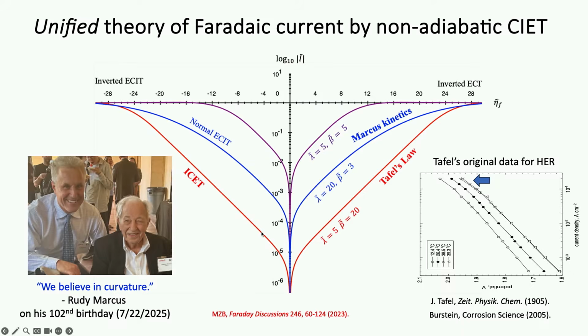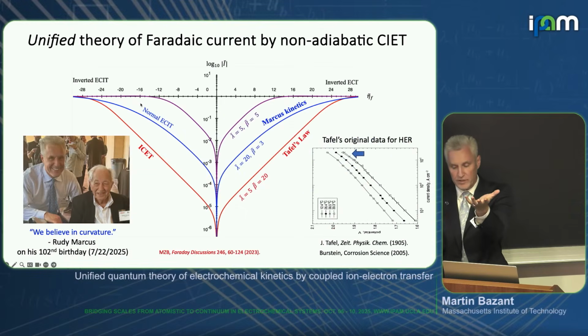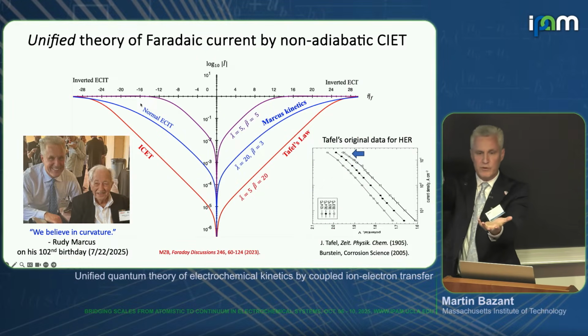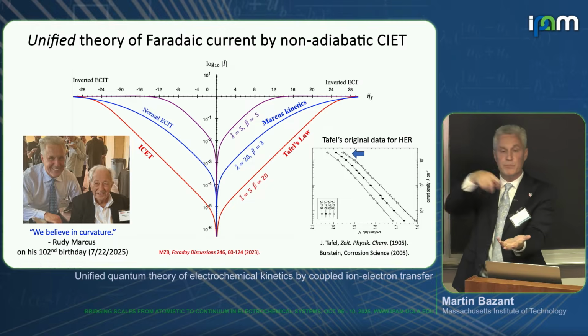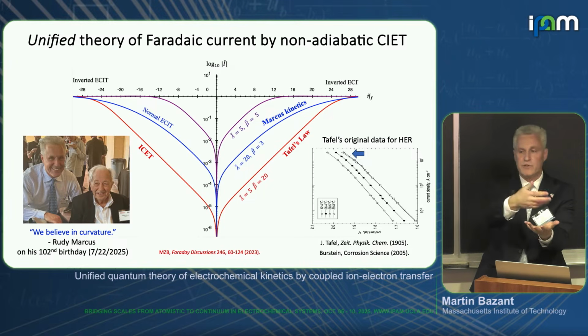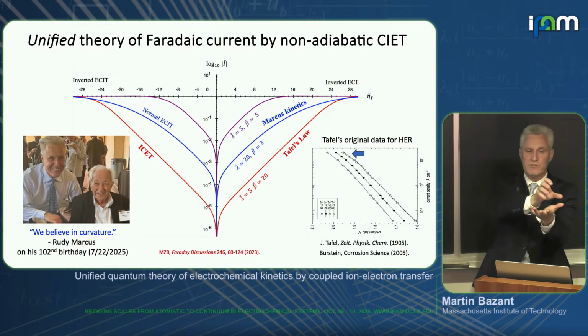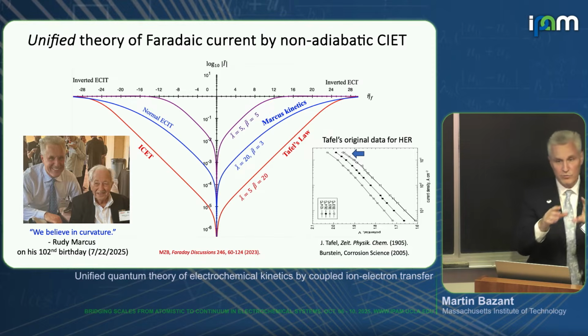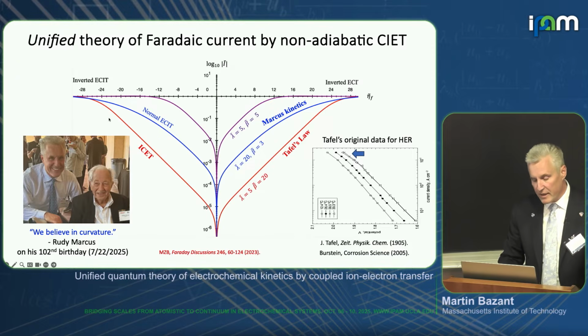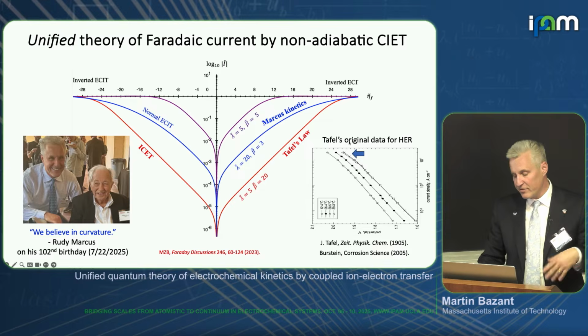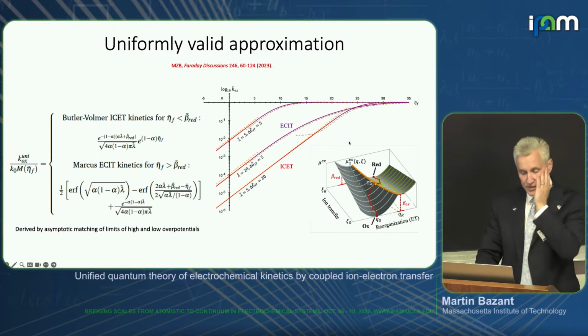This is because even in the cases where it's straight, you still hit this quantum mechanical limit. When the overpotential is big enough to tilt one barrier relative to the other one, eventually it's a barrierless transition, and it's entirely dominated by quantum mechanics of jumping from one well to the next with no barrier. I think that's what we're seeing, a little hint of it in that particular data.